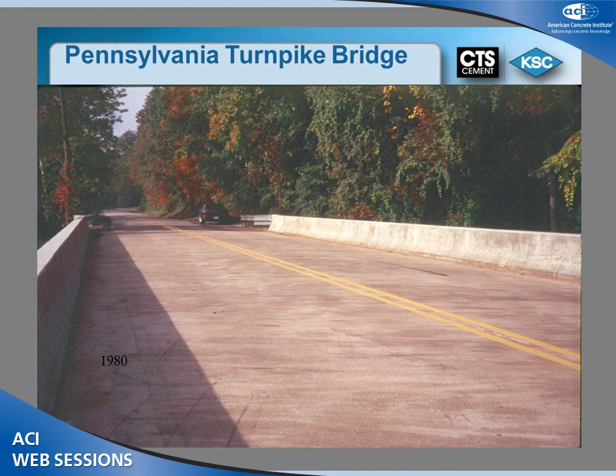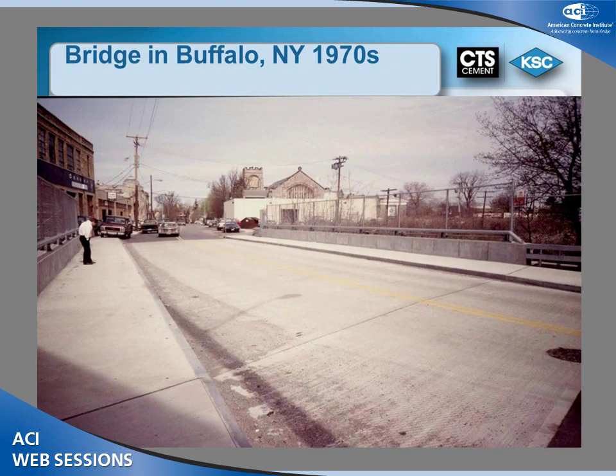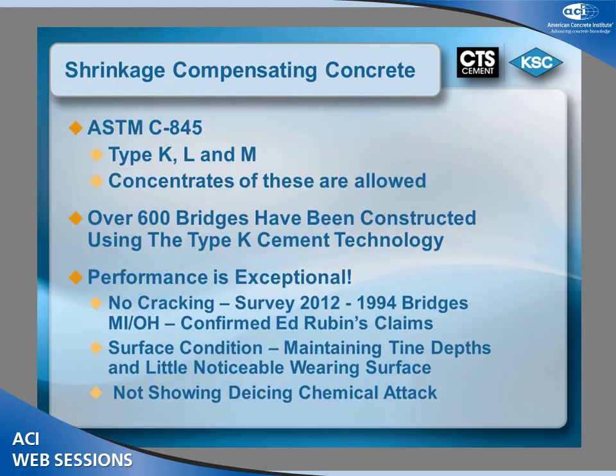The technology, we're looking at the Pennsylvania Turnpike in 1980. They did a number of bridges, somewhere around the neighborhood of 30 bridges, placed in the state of Pennsylvania. In the 1970s, this is in New York State. If you start looking at what the history is here, we start adding up these number of bridges, and you can start seeing that the numbers were back there in that age time. We go look at those bridges today, and we find that these bridges are still performing quite well, and in many cases have not had any type of repairs to the surfaces.